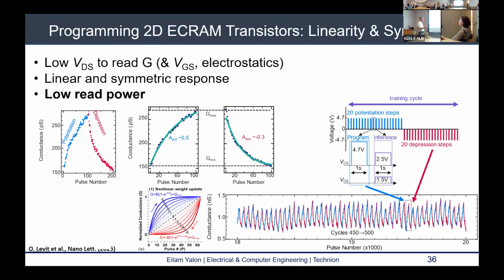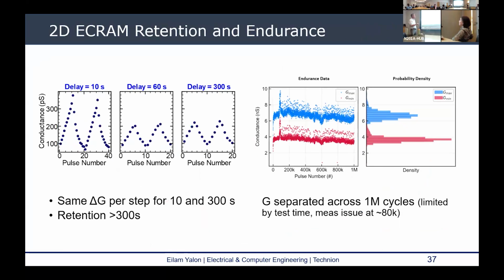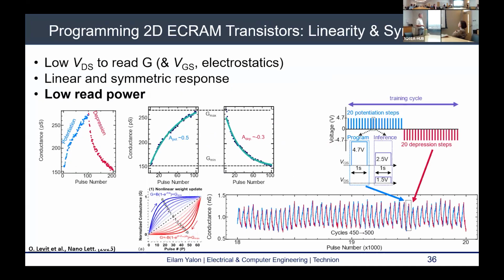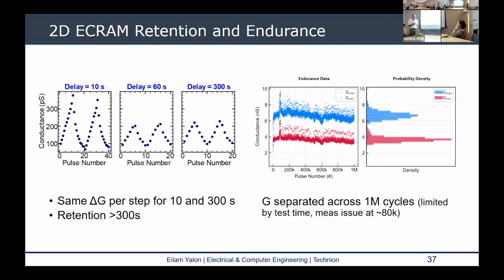And this is a demonstration of multiple cycles, and we went up to 1 million cycles. We had some issue with the measurement here, but I see 1 million cycles, a pretty stable measurement. The device did not fail; it was just limited by test time. So I think it could be fairly stable. And just showing the retention up to 300 seconds, again kind of limited by test time because it's a large number of pulses with long delays. So it's decent endurance and retention for these kinds of devices. The read power is fairly low because the conductance is just a few hundred picosiemens because of this transistor gating effect. So that's useful for these kinds of devices.